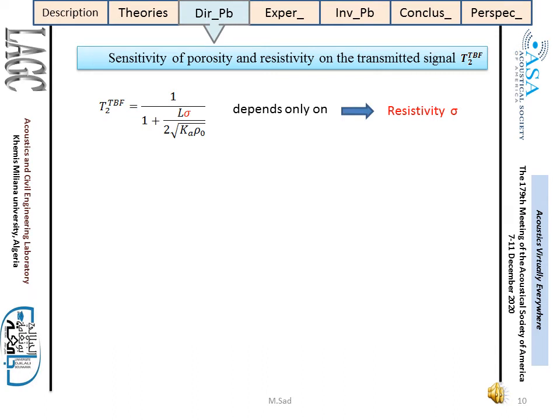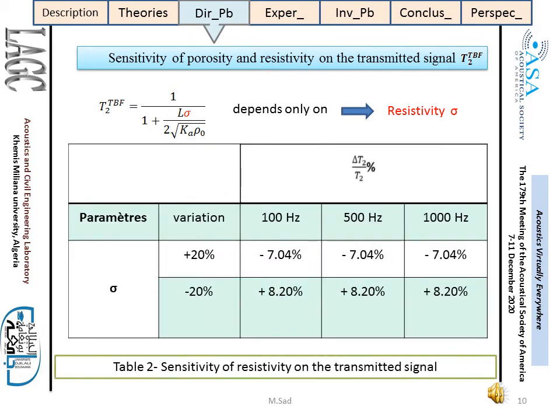The second expression of the transmission coefficient established at very low frequencies is the expression T2 given by equation 4. The advantage of this expression is that it's independent of the frequency and depends only on the flow resistivity. From table 2, we can see that the influence of resistivity on the transmitted signals is important at very low frequency and that this sensitivity remains constant as the frequency increases, because the expression of the transmission coefficient considered is independent of frequency. Based on this sensitivity study, we conclude that the flow resistivity has high sensitivity on the transmitted signal at low frequency and that this sensitivity is remarkable for both expressions of the transmission coefficient, T1 and T2.